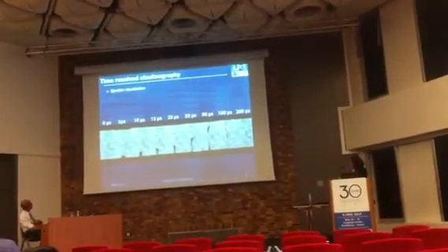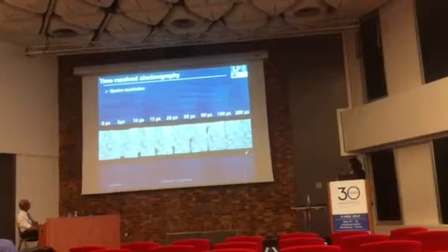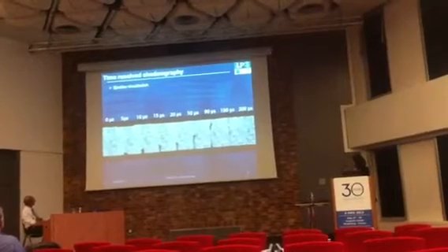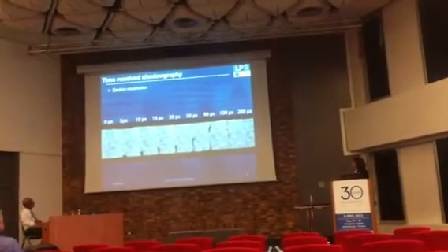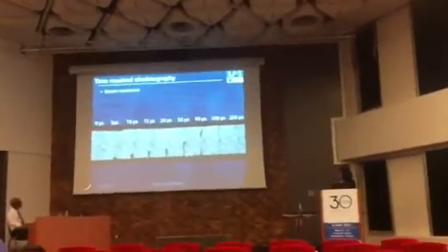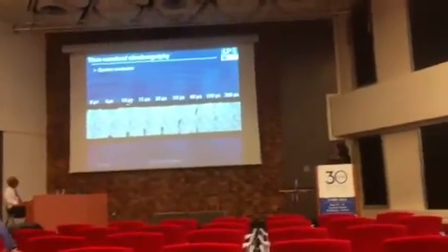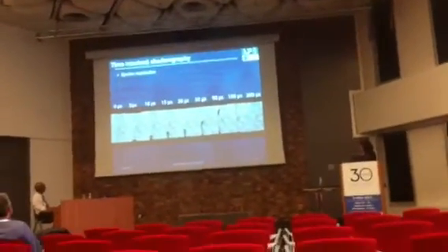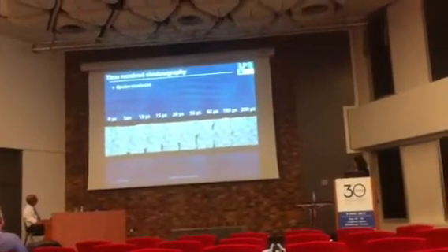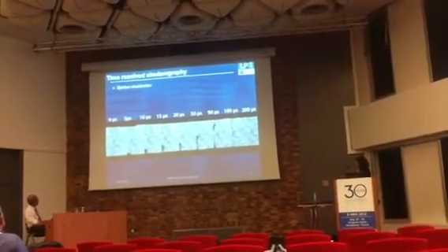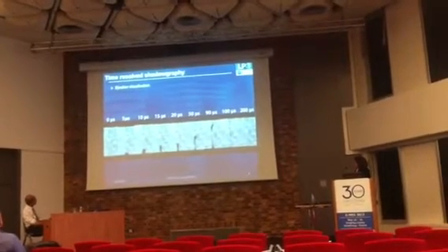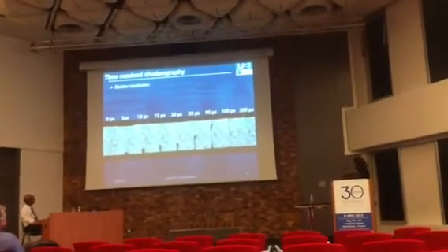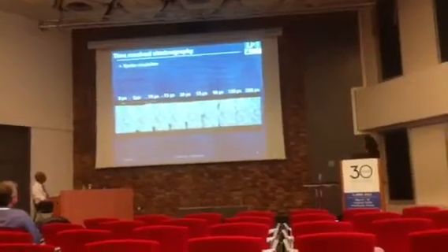We observe this kind of picture. Here, in this part, you have the donor substrate with our layer of material. Here is the receiver substrate. The distance between both is around 800 microns. And here you can see the ejection at different times after irradiation of the laser. At first, we can't see anything, but after 5 microseconds, we can see something is ejected here, and with increased time, we can see the droplet here with a little filament, and after 200 microseconds, we deposit something.